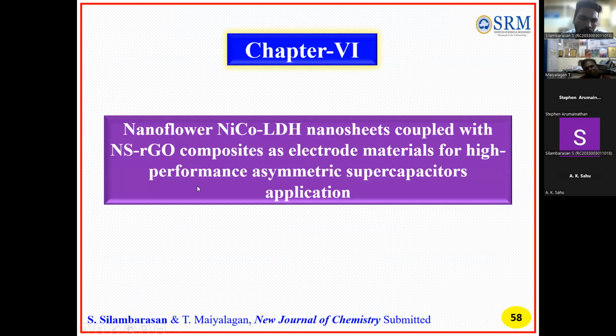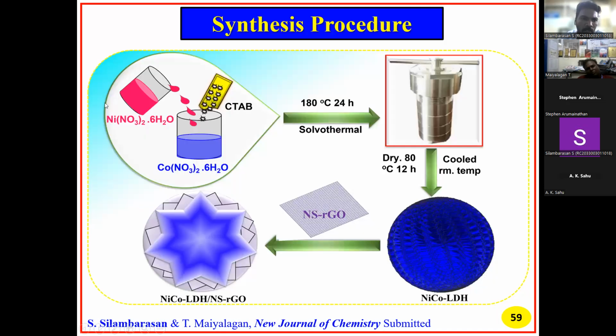Next, chapter 6, the nanoflower nickel cobalt LDH nanosheets coupled with the NSRGO composite as electrode material for high performance asymmetric supercapacitor application. For the synthesis procedure, the nickel and cobalt precursors were taken in a 1:2 ratio, and CTAB was used. The material was prepared by the solvothermal method, then 180 degrees for 24 hours in an oven. Finally, the prepared material was combined with NSRGO at 10, 20 and 30, so three variations were prepared. Finally, we got the nanoflower coupled with the NSRGO composite.